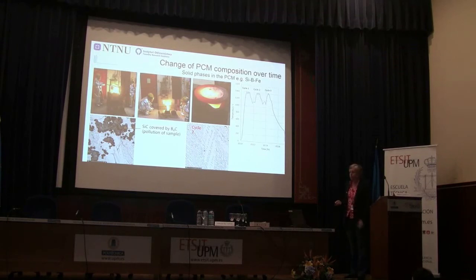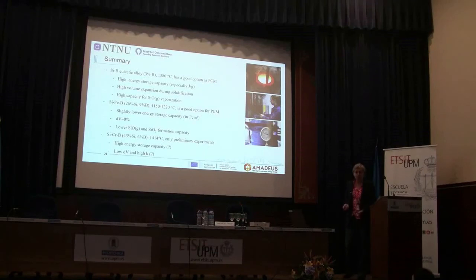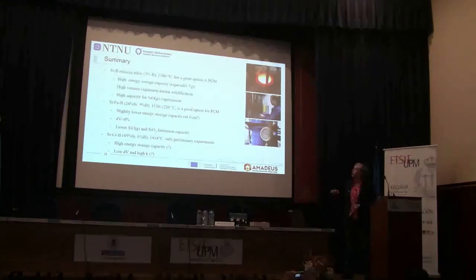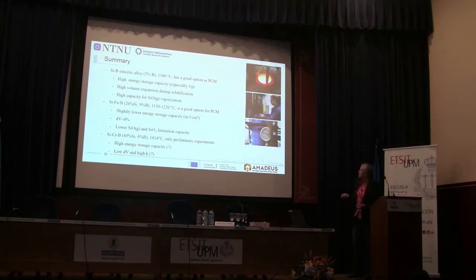So, finally, a summary of the presentation. We have investigated mainly 3 different alloys, silicon-boron with different amounts of boron. However, our favorite one is the eutectic alloy with about 3 weight % of boron. It should be 1385 here. It is a good option as a phase change material. It has a high energy storage capacity in joules per gram. However, the problem is the high volume expansion during solidification and also the high capacity for SiO vaporization, because the activity of silicon is quite high.